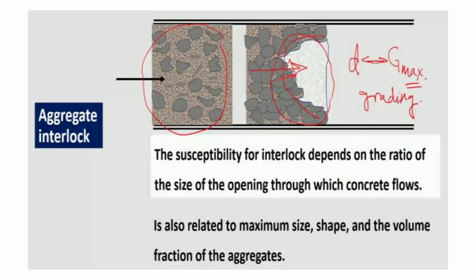So as you saw in the last diagram, as has been discussed, the opening size matters a lot. If the size is less, then definitely the amount of aggregate will be high. And if there is more aggregate, there will definitely be lesser interlocking because of lesser presence of binder. But if, as compared to this, either the size of the pore is large, or in this case the aggregate content is less, there is mortar everywhere. So that results in a good binding and aggregate interlock. Those criteria are of prime significance.